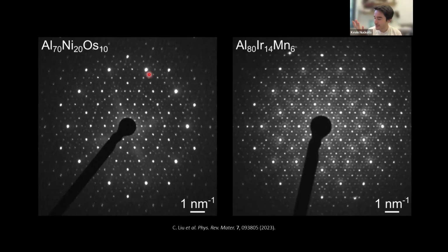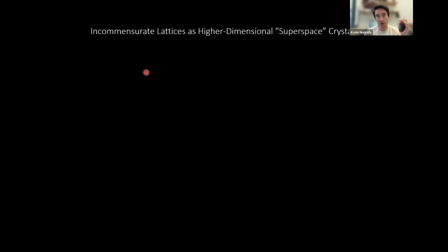If you look locally, the lattice doesn't look like it has all of the ingredients to constructively and destructively interfere to produce a sharp diffraction peak. And so this had people puzzled for quite some time, but theoretical physicists have solved this now with some really beautiful mathematical framework. What theoretical physicists recognized was that incommensurate lattices are not actually incommensurate, but instead they can be understood as projections of 4, 5, or 6-dimensional, higher dimensional lattices that we call superspace crystals.